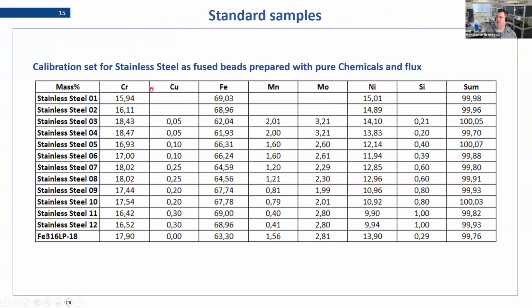And FLUXANA's idea with this recipe was that we made a calibration set for this stainless steel in this case, but also for the other materials mentioned before. We made this basically from pure chemicals. We took a look at the range, and we made these 12 calibration standards just based on pure oxides to get these mixtures. And there is a standard available down here, which was used then. This was actually quite new at that point. It had just come out.